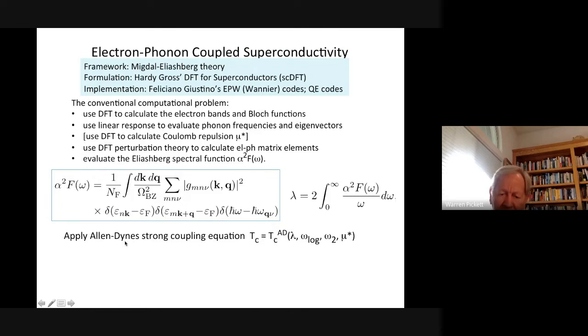Dynes was taking tunneling data from which you can extract alpha squared F experimentally. And Allen was doing the theory, solving the Eliashberg equations and fitting the results to a simple function. It doesn't look simple, I'll show it to you. But it's a simple function of these parameters. And in fact, if you want to ignore the difference between these two frequency moments, that's okay for basic understanding. Mu star is a Coulomb repulsion constant, which usually is not known exactly, but it's typically between 0.1 and 0.15. It accounts for the Coulomb repulsion between the two electrons that are being attracted by the phonons.